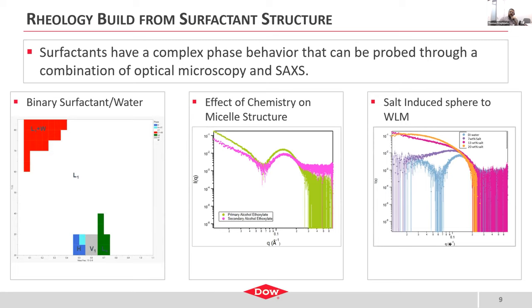Now, when you get even above 75 weight percent, you go back into a non-birefringent phase. And what that actually is, is an inverse micelle phase, where you have surfactant micelles where now the greasy hydrophobe is the continuous phase, and any water that is in the system is trapped in the hydrophilic core.